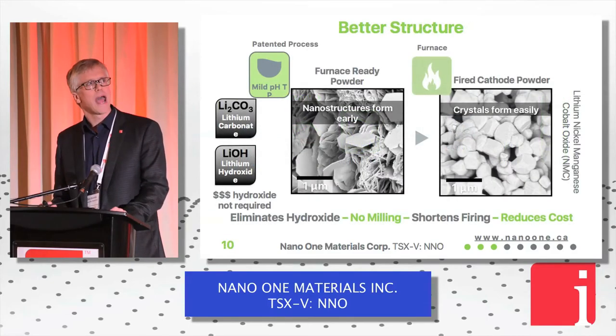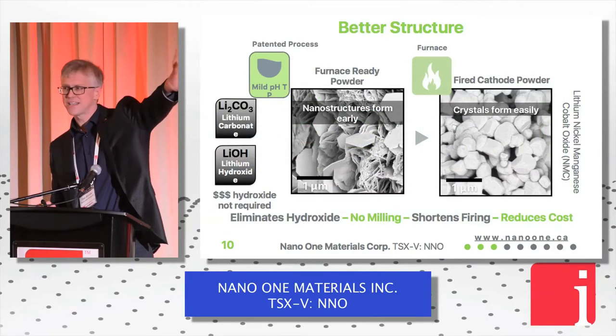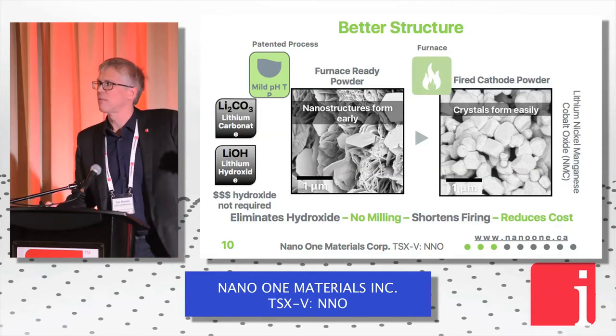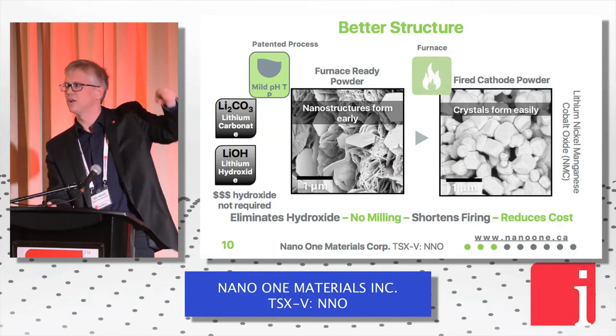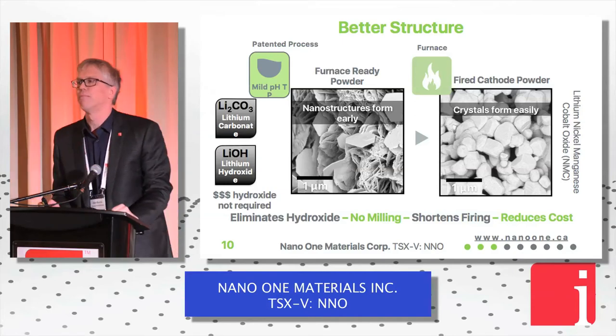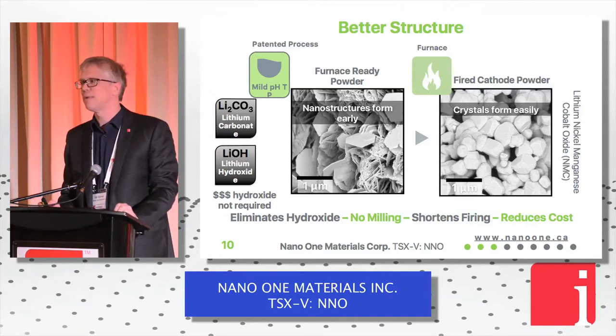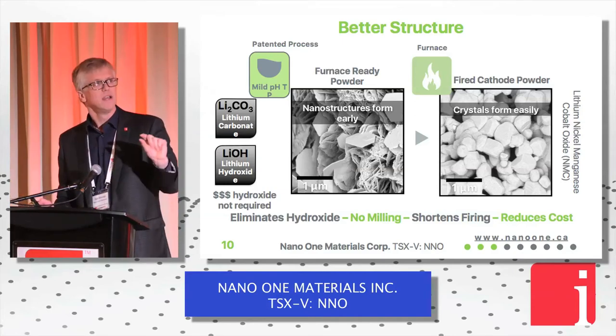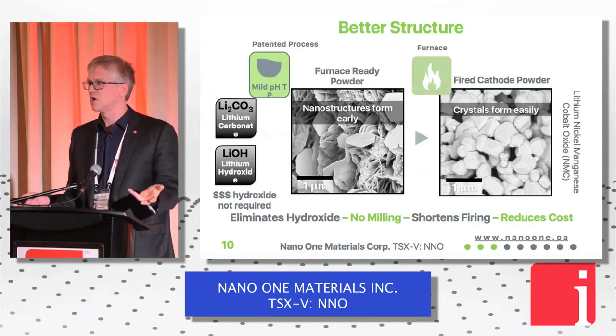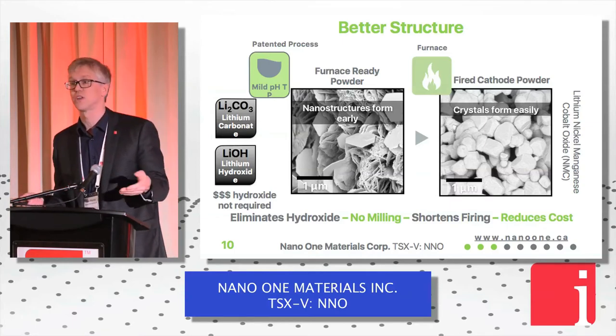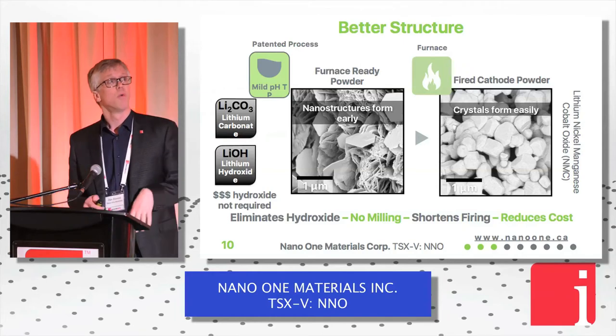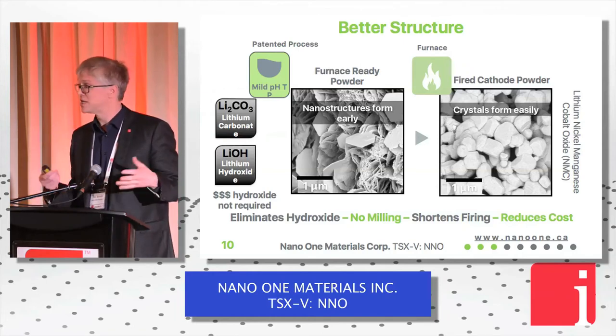What comes out of our reactor is a structured material. So that's the powder under a scanning electron microscope, and you can see those look like hexagonal chips. They're about 10 nanometers wide, which is about 50 atoms thick. And those structures, those hexagons, are an indication that we're forming crystal structures before we get to the furnace. Once we go through the furnace, it forms an entirely different structure.